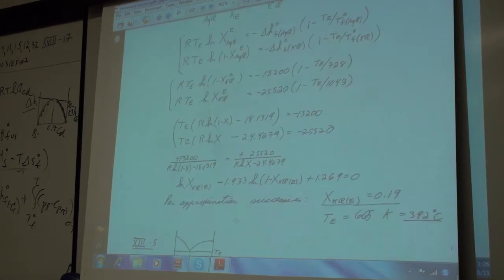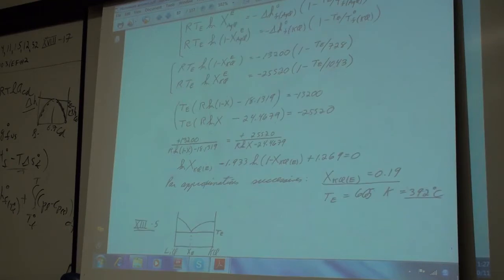And it comes out actually fairly close to the actual. You solve the 2 by approximation, by successive guessings. You end up with 2 equations here, logarithmic equations. You can just take successive approximations and narrow in on the right answer within a couple of minutes. I think this is within about 15 degrees and a couple of % of the actual point, so this is actually a fairly ideal system.